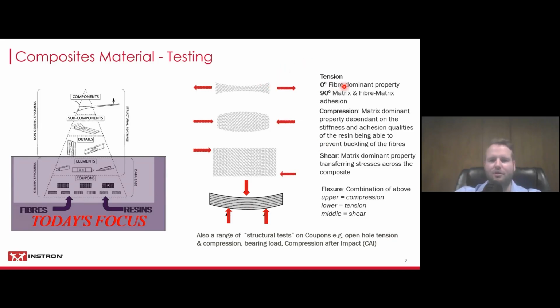Tension, if the fibers are oriented in the 0 degree direction, or direction number 1 in our example, is a fiber dominant property. And in the 90-degree direction, that is, as mentioned earlier, the matrix and fiber-matrix adhesion property. And in compression, it is really dependent on how well the matrix can prevent the fibers from buckling, and the adhesion qualities between the resin and the fibers. And shear is a matrix dominant property, really depending on how well the shear stresses can be transferred across the composite material, and then flex is a combination of all of those.